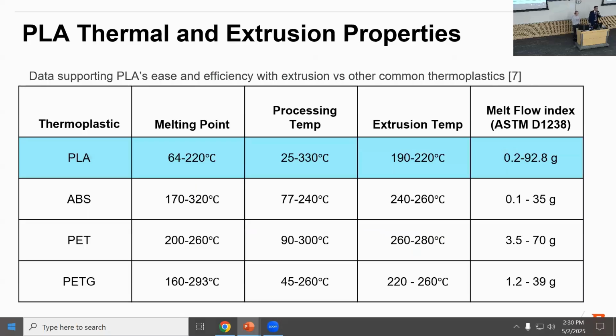So PLA has really beneficial properties for making it easy to extrude. It was compared with ABS, PET, and PETG, which are three other very common thermoplastics used for 3D printing. And the melting point, processing temp, and extrusion temperature for PLA is lower than all of them, which is good for how easy it is to extrude. It takes less time to heat up your extruder and is just more energy efficient.